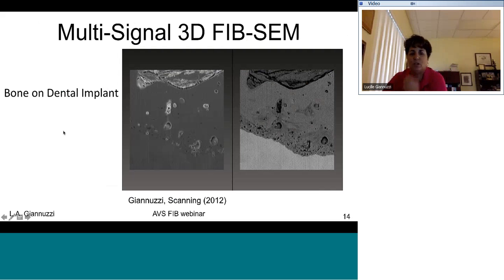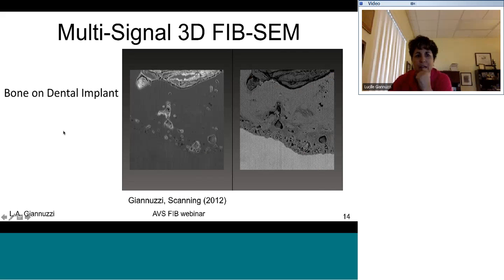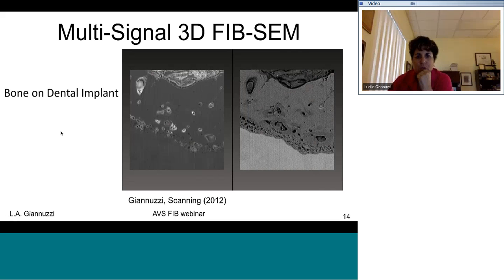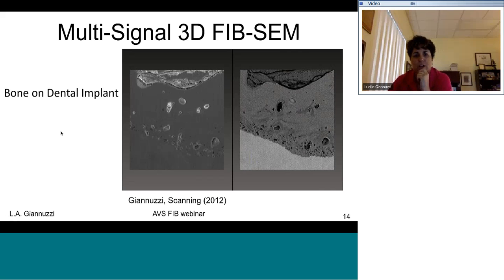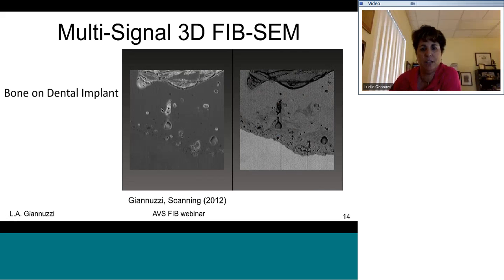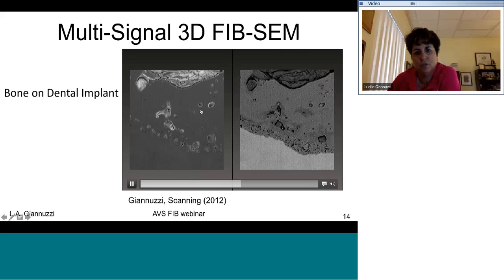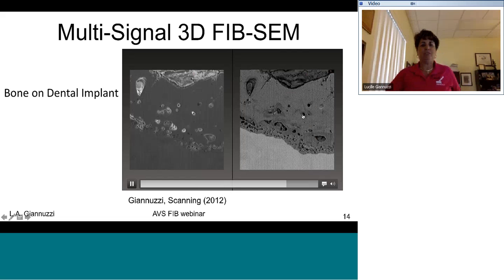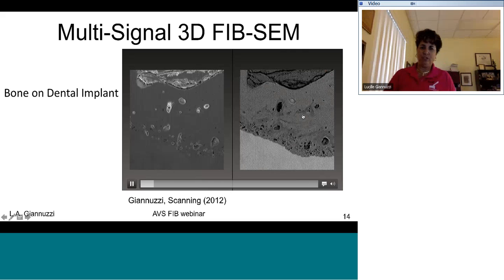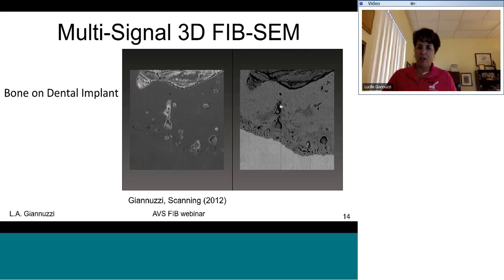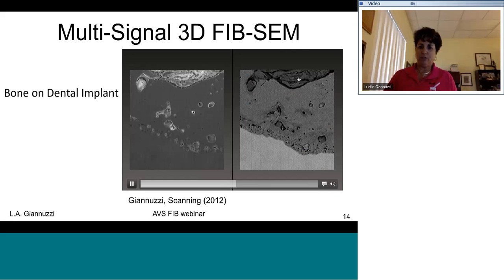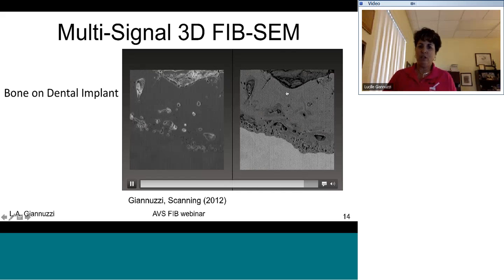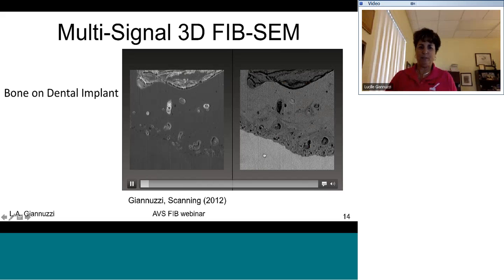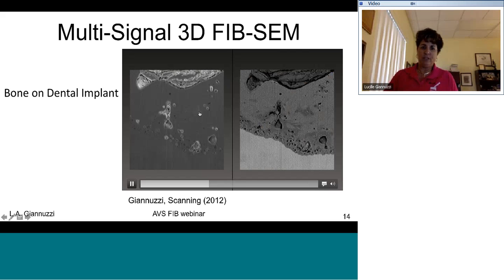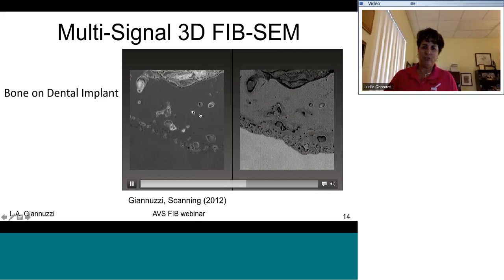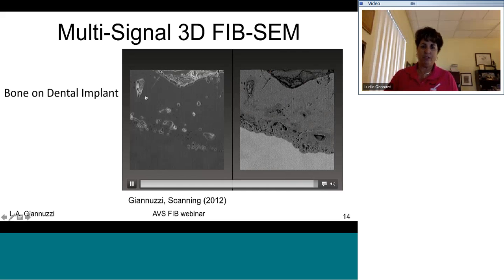So this is some work I did several years ago, a few years back, using multi-signal SEM imaging on a single slice. So this is bone on a dental implant. So this is the secondary electron imaging on the left, the backscattered electron imaging on the right. And what you see is that the different signals will give you different information. Obviously, you get the really nice material contrast on the right, so you can see the bone, you can see the ceramic coating, and then you can see the titanium implant. Whereas the secondary electron signal shows the edges of the pores in the ceramic coating very nicely.